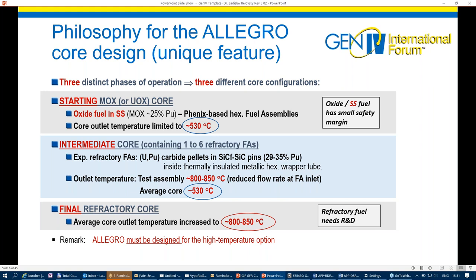And when having the refractory fuel well proved for full scope operation, then the final full refractory core will be loaded and Allegro will be able to be operated at the target temperature around 800 degrees C. It means that all the technology which can't be replaced must be designed from the very beginning for the high temperature option.